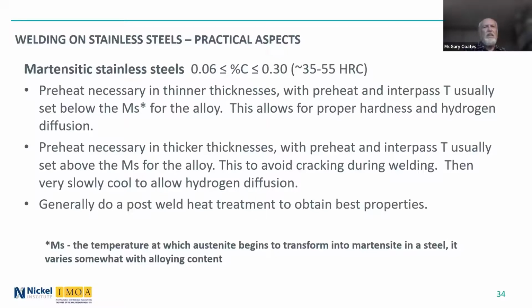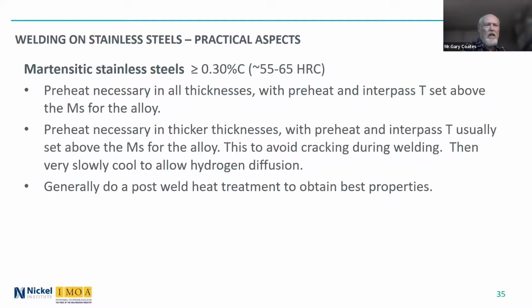Generally, for the intermediate carbon alloys, you do want to do a post-weld heat treatment, even if it is just a tempering operation, to get the best properties. And finally, we come to the higher carbon martensitic stainless steels. Obviously, when you get to Rockwell C55 to 65, they are very, very hard. They are very, very brittle. You do need to preheat for all thicknesses with an interpass temperature above that Ms line.